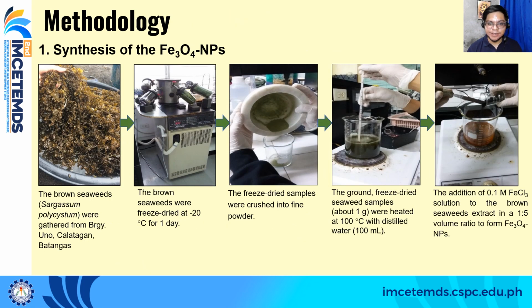As for the methodology, first is the synthesis of iron oxide nanoparticles, which is a crucial part of this study. We collected the brown seaweeds from Barangay Uno, Calatagan, Batangas, where they do have brown seaweed farming. The brown seaweed was then freeze dried at negative 20 degrees Celsius for a day, where we brought the samples to De La Salle, Manila, and then transported back to Batangas State University for immediate experimentation.